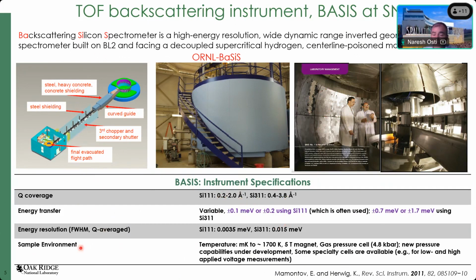Furthermore, we also have different types of sample environment available. For example, in case of temperature, you may go from millikelvin all the way to 1700 Kelvin. You can also use a magnetic field on your material. You can also pressurize it. We have a gas pressure cell available, where you can compress the gas using up to 4.8 kilobar pressure. And we are also developing some other pressure capability in the instrument.